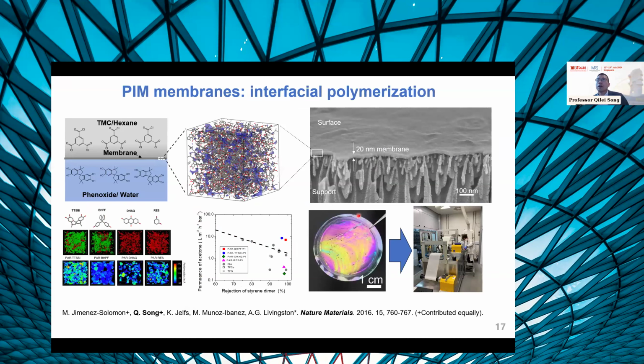At Imperial College, I worked with Professor Livingston during my postdoc. We developed these PIM materials by interfacial polymerization. By combining the PIM monomers with the interfacial polymerization technique, we were able to develop these cross-linked PIM materials. And because they are cross-linked, they are stable towards solvents, so we can use this for organic solvent nanofiltration. This is really exciting because the interfacial polymerization reaction can give 20 nanometer thin membranes. This is still a great achievement, in my opinion, after almost 10 years. This paper got a lot of citations in the community.